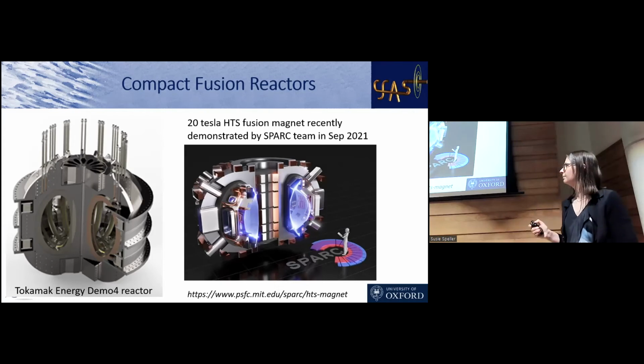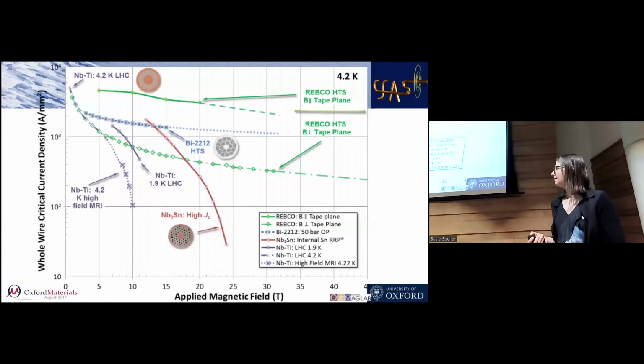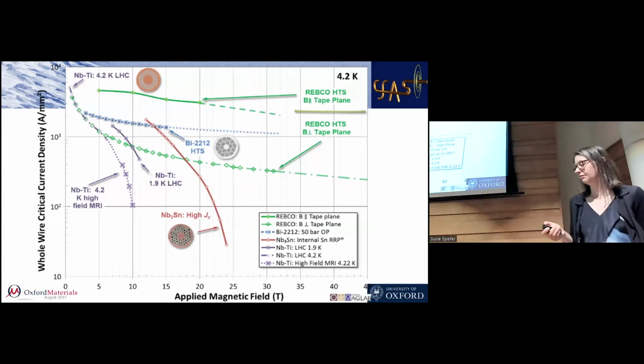Now, that again probably doesn't mean very much. This is a very famous graph that lots of people who work on superconductors have seen lots of times before. It tells you how much current density you can get through a material as a function of how much magnetic field it's sitting in. So if we look at niobium titanium, which is our favorite superconductor because it's cheap and easy to use, it sits down here, which means it's fine so long as we're not at very high magnetic fields.